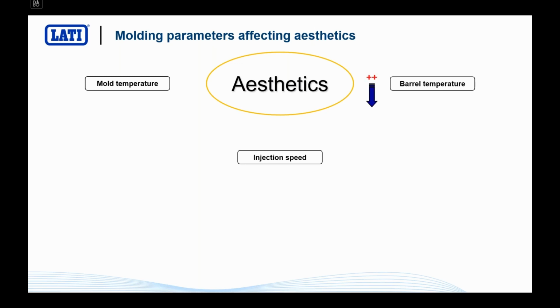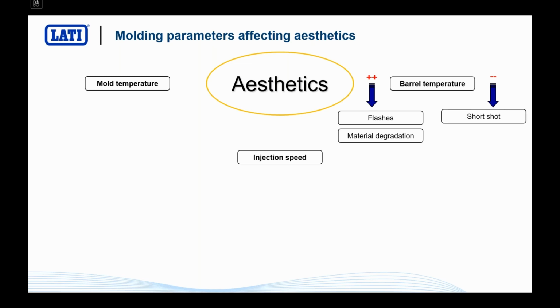What happens if the temperature of the barrel is too high? If the temperature is too high, we will have flashes. It means that the plastic will be too liquid and will just be squeezed between the two halves of the tool. Or you can actually destroy the material in itself. If the barrel temperature is too low, you can run the risk of having a short shot, which is a not completely filled part. And it's absolutely a no-no. You do not want to deal with that.